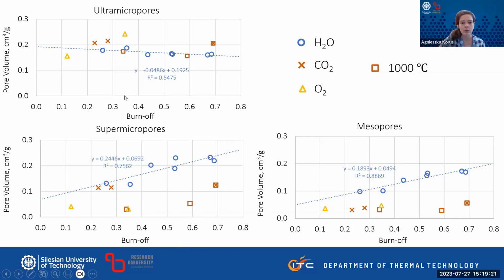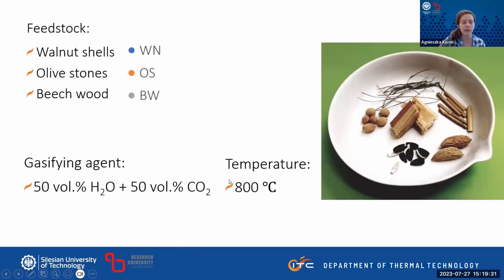But based on this, we decided that we definitely need to use CO2 at as high a concentration as possible, and also limit the temperature to this 800 degrees, not going any further. So these were the gasification parameters that we used for char preparation.